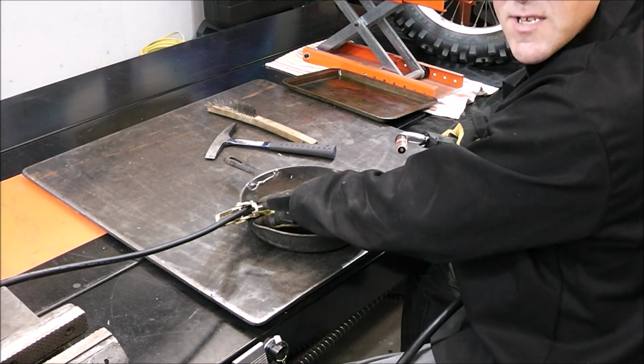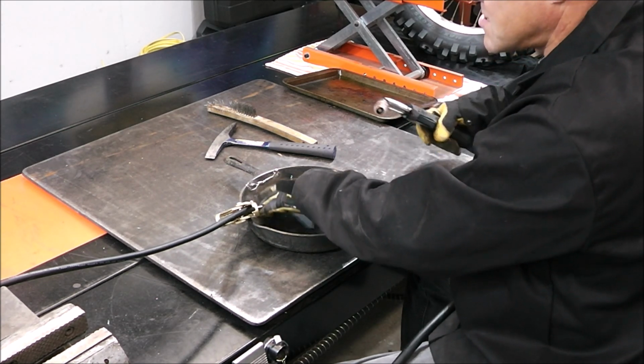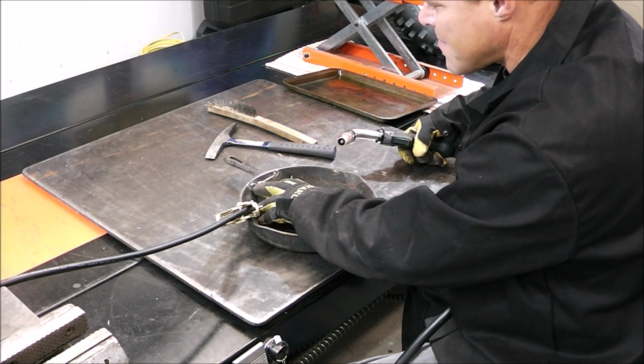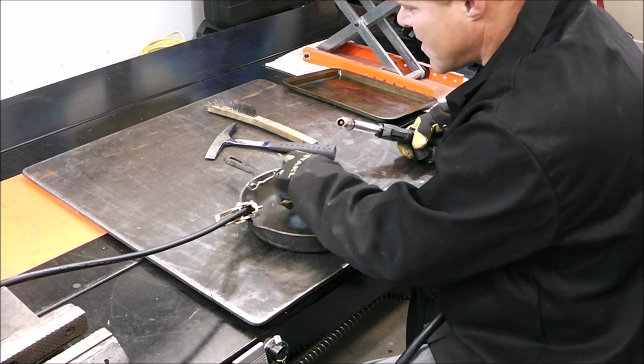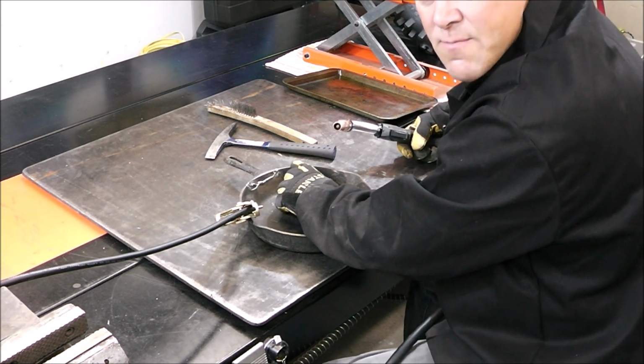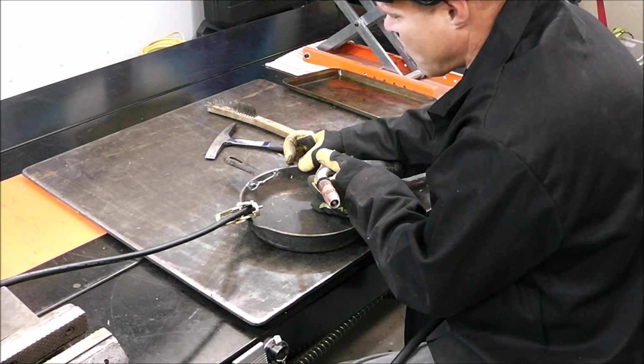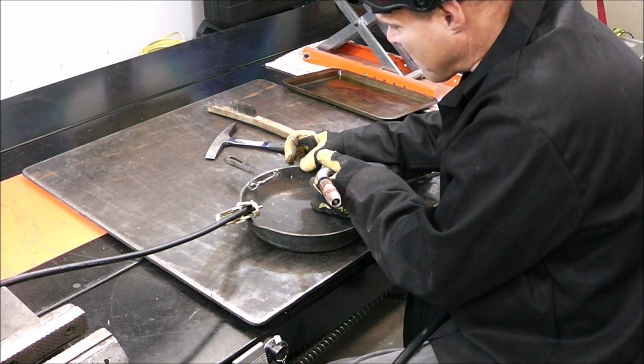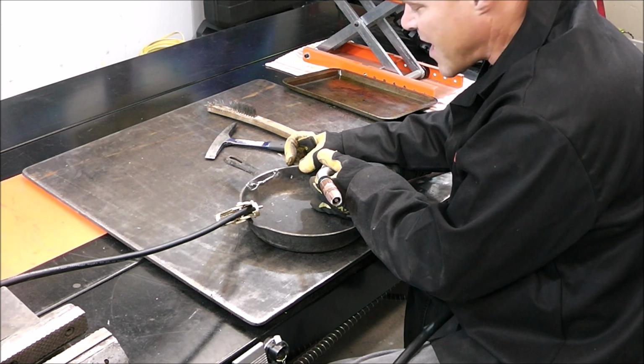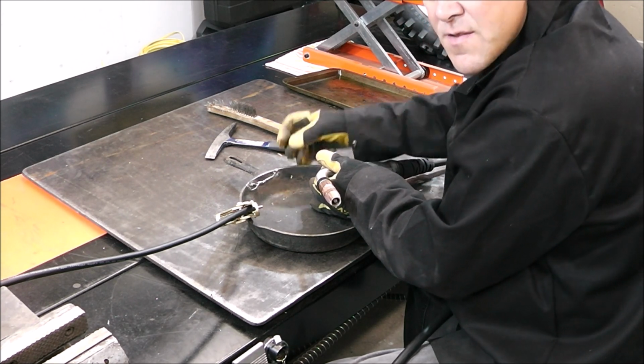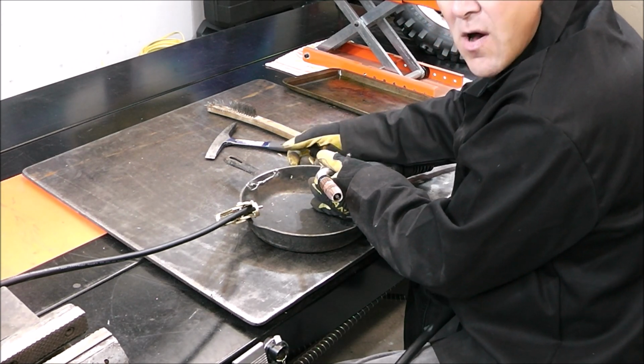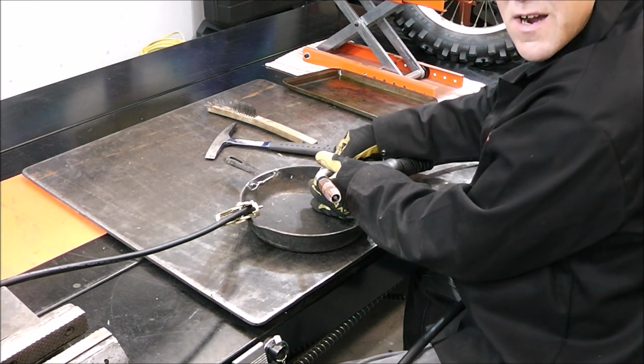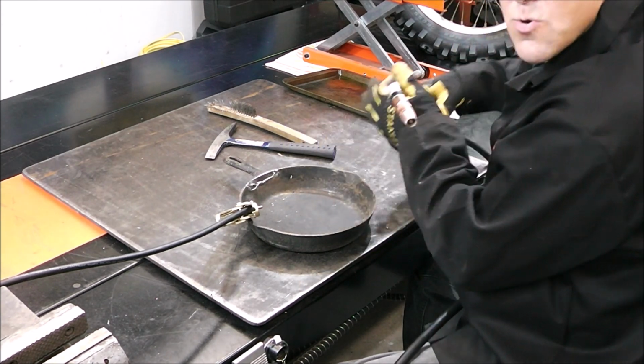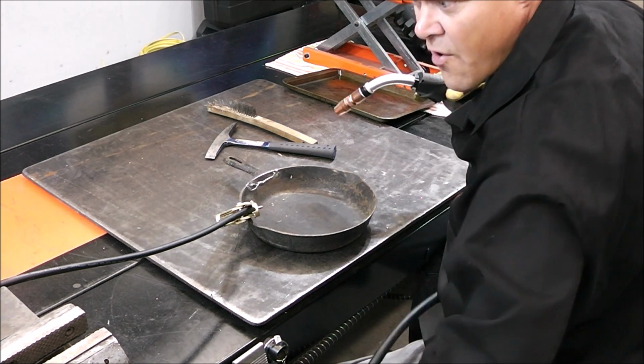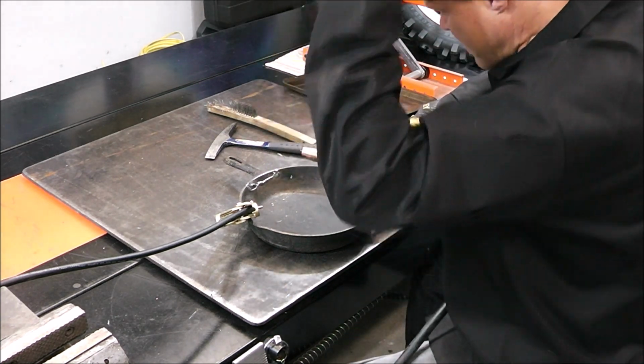When you weld cast iron, one of the test methods to determine if it is cast iron is, if you have a TIG welder, turn your amperage right up, crank it right up, and with no filler wire, hit it right on the corner of a piece of this cast iron, make a little ball, then run a file over it. If that ball is hard, then you know it's cast iron. So cast iron hardens when you weld it. That's why generally it will crack and fail again later down the road.